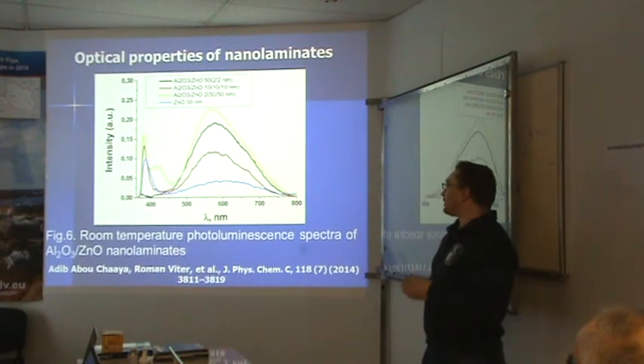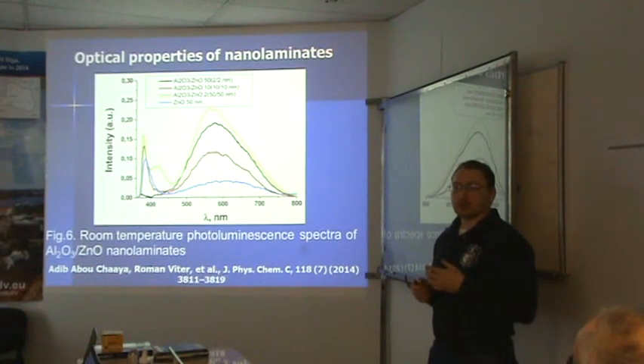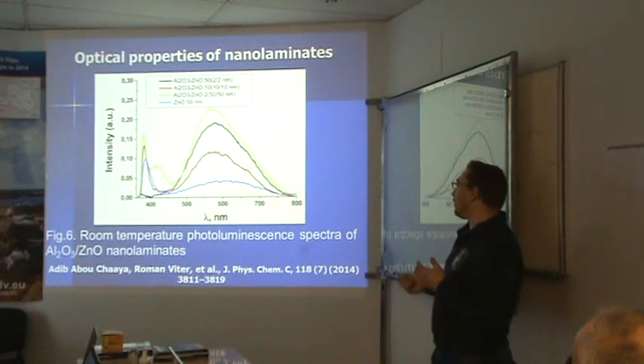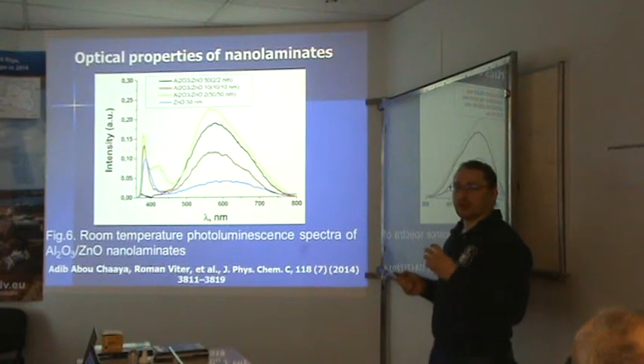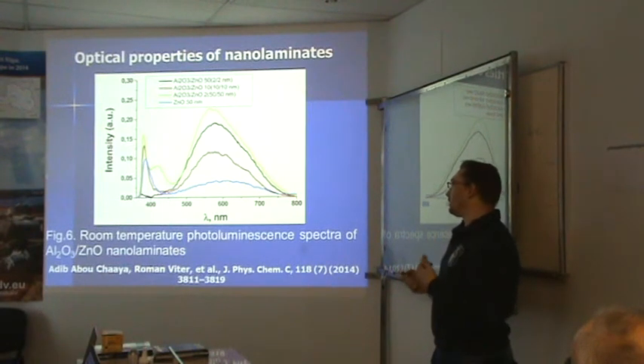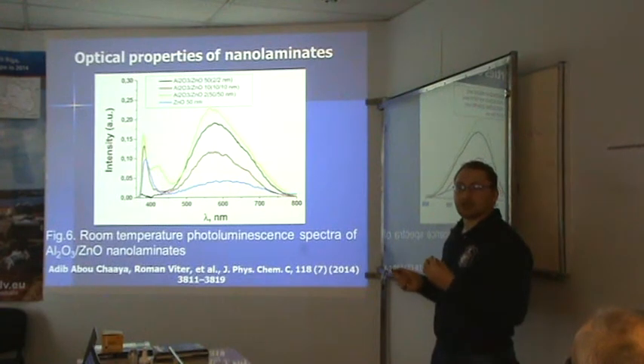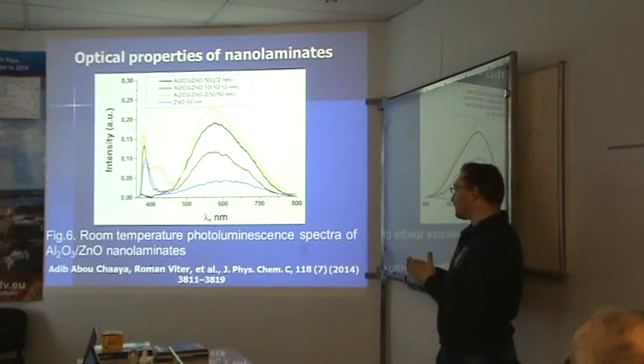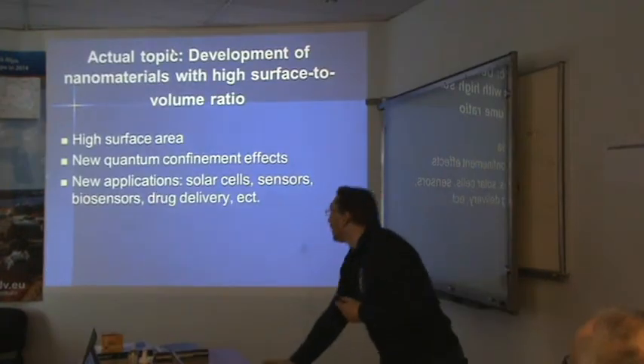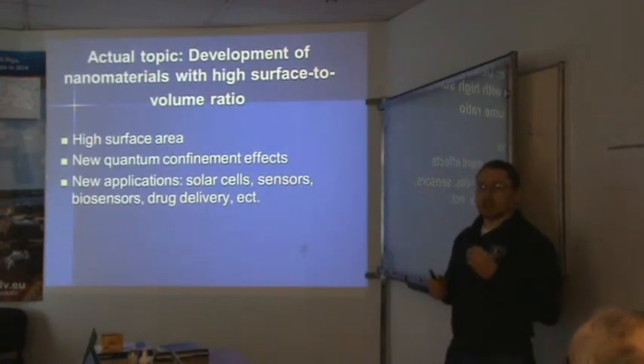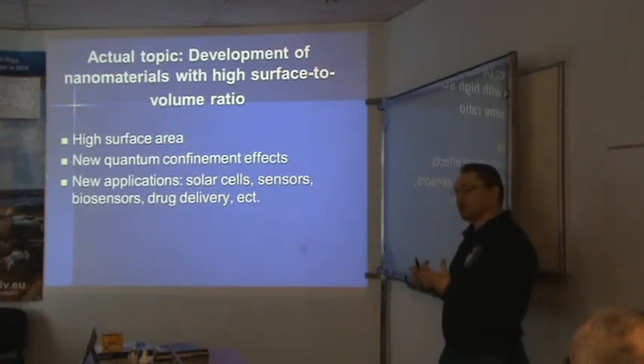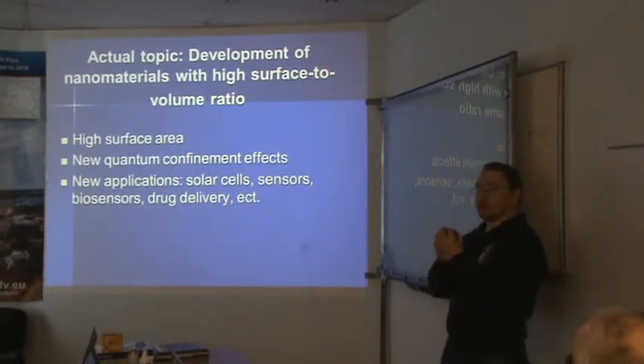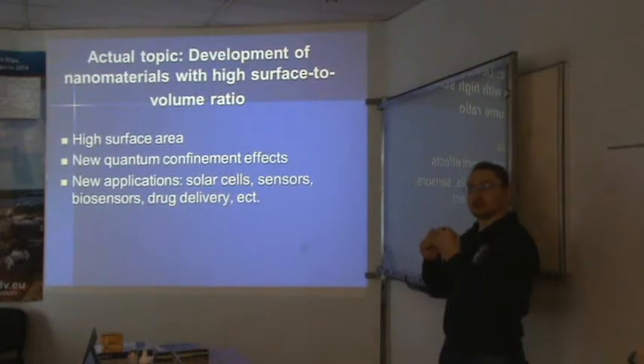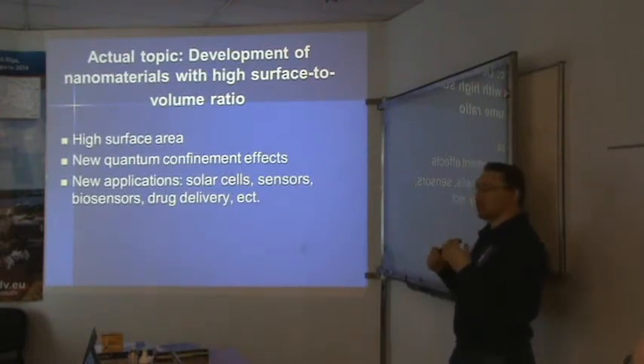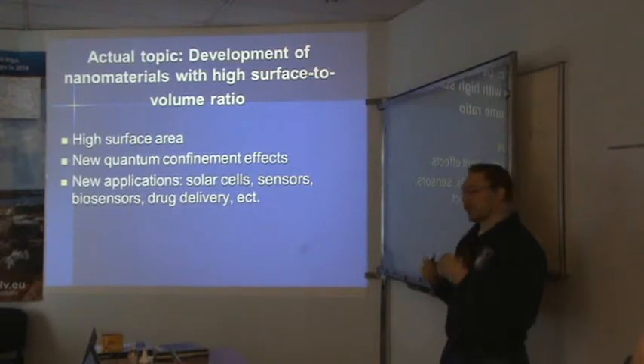And the most interesting things were observed for photoluminescence. We had enhanced photoluminescence even for 2 nanometer thin films, and it was affected by the change of the structure. So it was the way to tailor the properties of these nanostructures. But for practical application, it's important to develop nanomaterials with high surface to volume aspect ratio, because when we want sufficient effects, we need to increase the active surface, and we need to increase the role of the surface in these nanostructures.